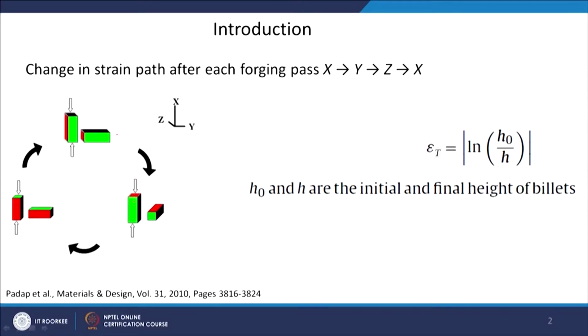Then in the next cycle, now this particular dimension is the longer one, so we are going to deform on the red plane, and you are constraining the deformation in the direction perpendicular to the black plane. Now you can see lengthening is in the direction perpendicular to the green plane. The next deformation will be on the green plane, and you are allowing lengthening in the direction perpendicular to the black plane, and again you have come to the first stage. So, one complete cycle requires these three passes. In multi-axial forging you will always see any property shown in multiples of 3: 3, 6, 9 and so on, because you will reach the initial stage only after these three deformation passes.